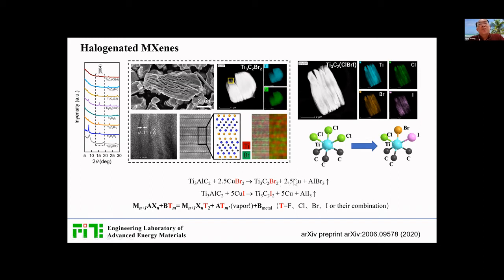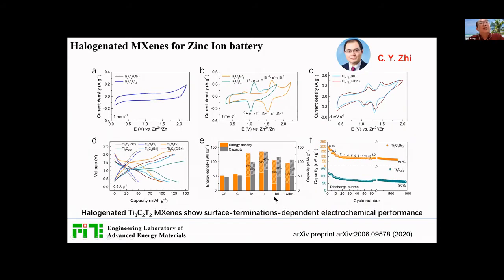Moreover, we can combine these groups together, so in these MXenes we can see all these halogenated MXenes containing chloride, bromine, and iodine. So what's the advantage of these new MXenes? Here we tested in a zinc-ion battery with the help of Professor Zhi. We see from figure A that there's no electrochemical activity in the traditional MXenes, including the chloride one. But for the iodine one and the bromine one, you can observe some redox peaks here. And this redox of the terminals can contribute to the energy density and capacities.